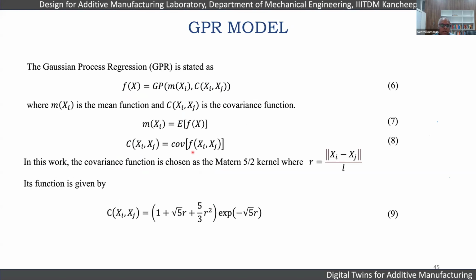For the GPR model, one of the very important things is how to do the hyperparameter tuning. So we use the Matern 5/2 kernel function. After we tested so many different functions, we found the Matern 5/2 kernel function to be more effective in the case of temperature prediction, right? We have seen this during our hyperparameter tuning. This is the covariance function that we have used in the Gaussian process model.